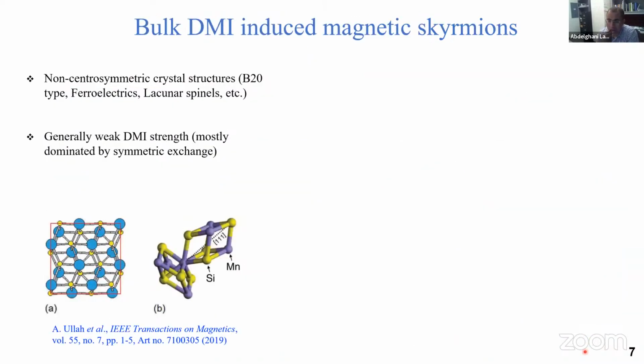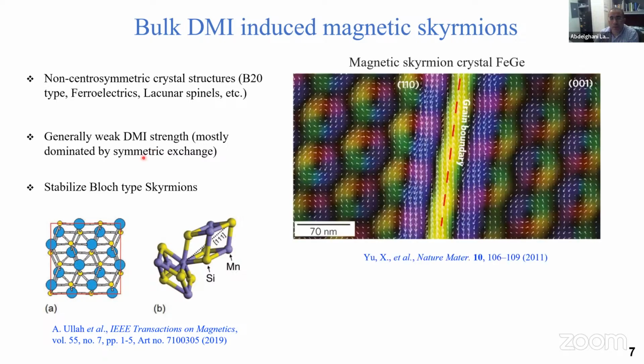So far, I talked about skyrmions, but usually these skyrmions exist in systems with what's referred to as bulk DMI. For bulk DMI, we have a noncentrosymmetric crystal structure, the so-called chiral B20 crystals, and also certain ferroelectric or lacunar spinels. In general, in this case, you can create this DMI. Usually DMI is kind of weak because it's dominated by the symmetric exchange. In this case, you can also stabilize these Bloch-type skyrmions, as demonstrated in many systems.